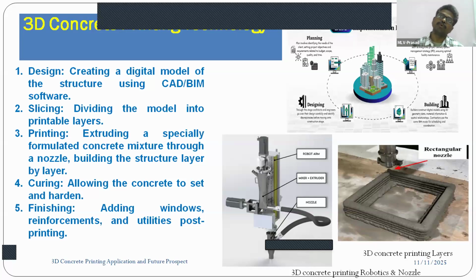Even if you are not able to go for developing an automated mode, where if you give the command it works automatically, suppose you want to do a layer manually, you take a hopper type shape, and from that you arrange the nozzle from your end. The nozzle opening, you can fix your size like 3 mm, 4 mm, 5 mm, or 6 mm, whatever size of the thickness of the layer you want.